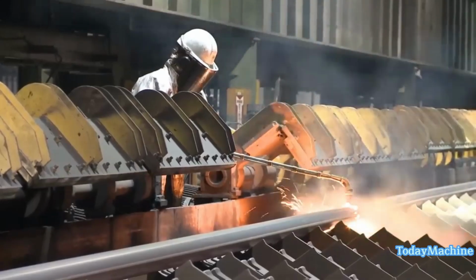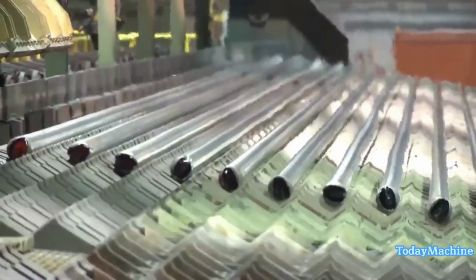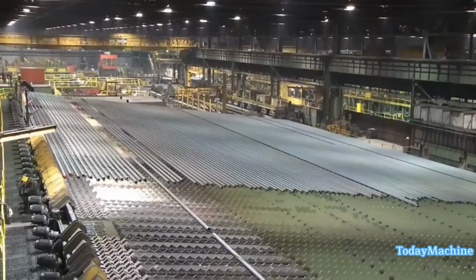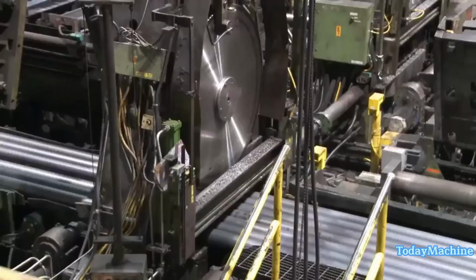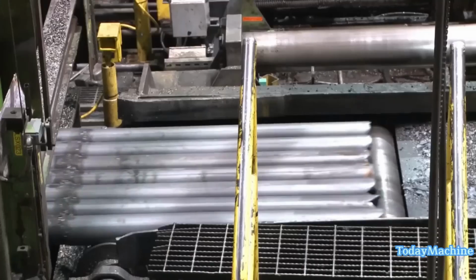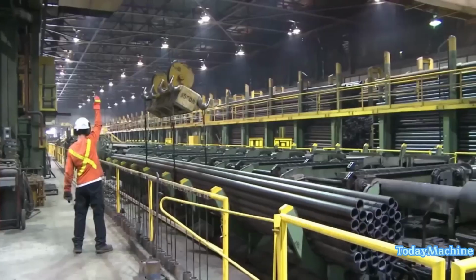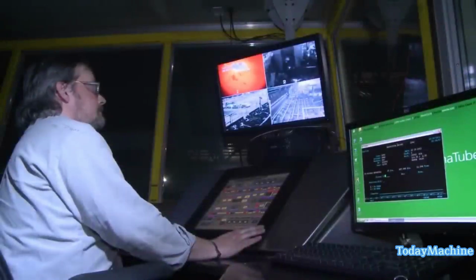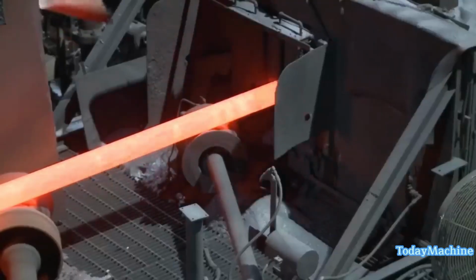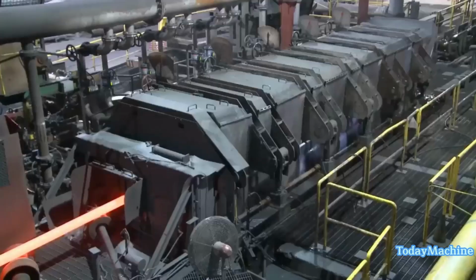The hot-rolled tube is discharged onto a cooling bed, where samples are cut and sent to the on-site lab for testing. Individual pipes are cooled to ambient temperature before their ends are cropped at the mill's cold saws. The pipes are then transported to the heat treatment line for quenching and tempering.